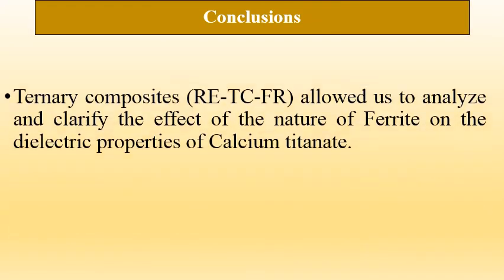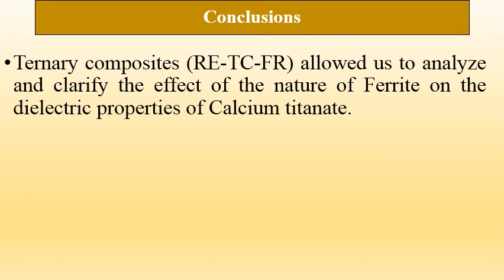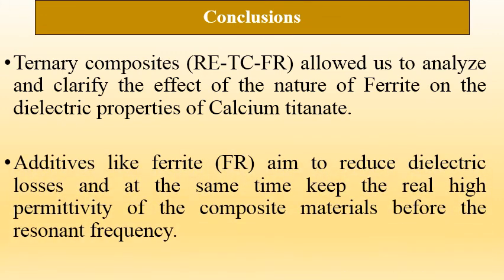Finally, we conclude that ternary composites allow us to analyze and clarify the effect of the nature of ferrite on the dielectric properties of calcium titanate. Additives like ferrite aim to reduce dielectric losses and at the same time keep the real high permittivity of the composite materials before the resonant frequency.